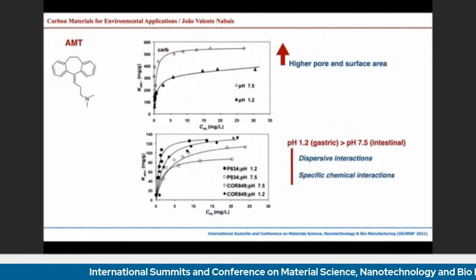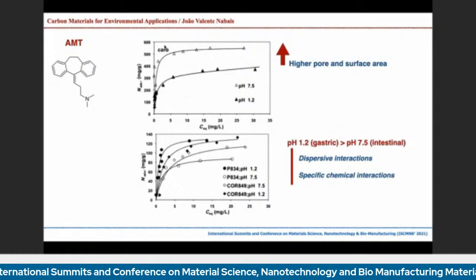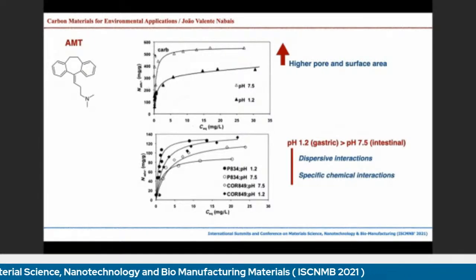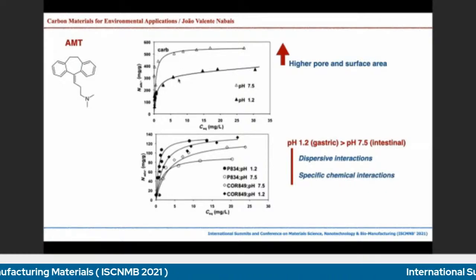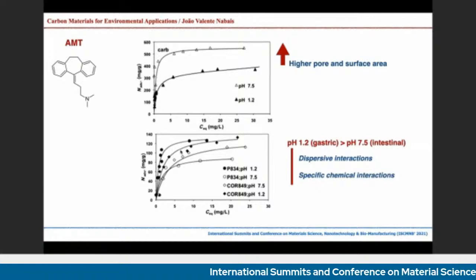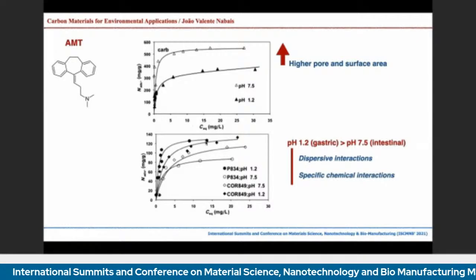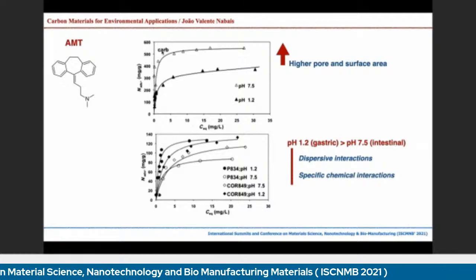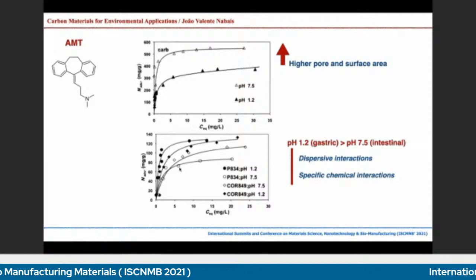So regarding AMT again, this is the carbon mix, and the carbon mix, of course, has a higher absorption capacity, which is around 500 at pH 7.5, 300 at pH 1.2. Our carbons reach a maximum of 120. So what does it mean? It means that, if you remember, the porous characteristics of the carbon mix are much higher than our material. That's why the absorption is higher.